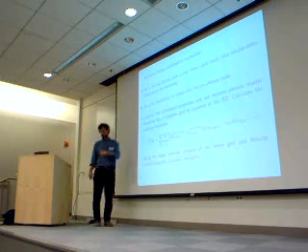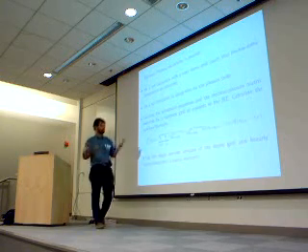The reason why this is convenient is because when you move across the Brillouin zone, the eigenmode may change and may get some phase, and you may have levels that are degenerate, and then when the symmetry is reduced they become non-degenerate.